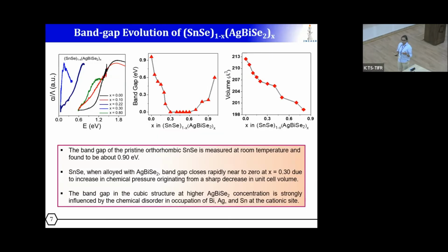Now I have studied the band gap of these materials, and I have seen that with increasing AgBiSe2 concentration, there is a monotonic decrease in the band gap, and suddenly upon 30 mole % of AgBiSe2 alloying, the band gap closes to almost zero. This is because of the increase in chemical pressure, which originates from the sharp decrease in the unit cell volume.